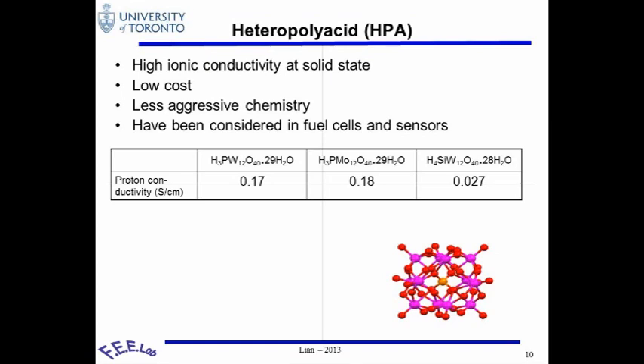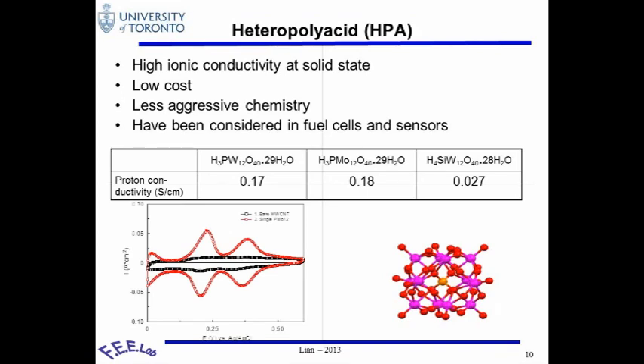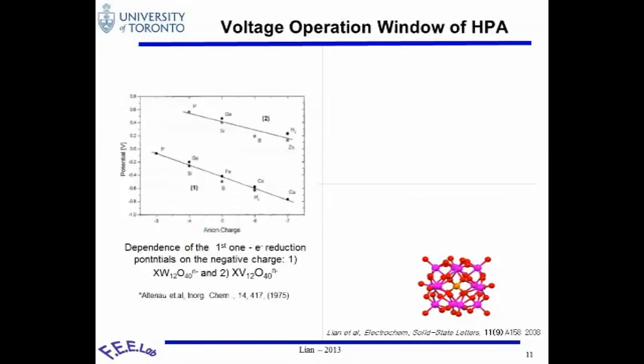However, for those familiar with this material, there is a problem, because this material has sometimes been used as an active material. They can use it to modify carbon or modify the electrode, adding redox reaction. So why can this be used as an electrolyte that shouldn't have electrochemical activity but just ionic conductivity?